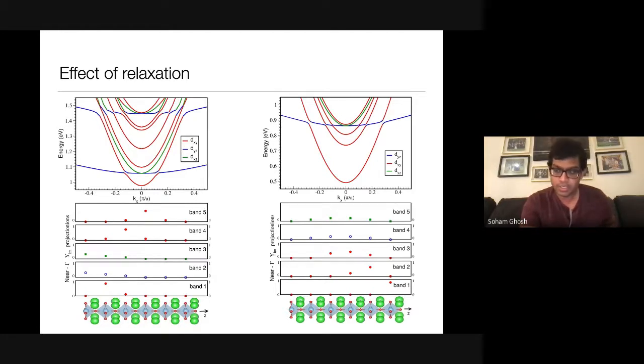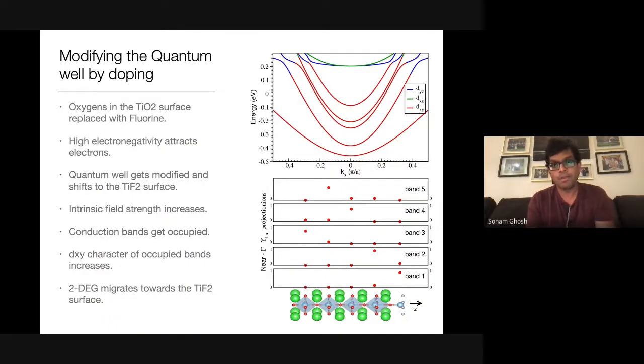And so what you see in these boxes, what I call band 1, band 2, band 3, band 4, and band 5, are corresponding to these points that go from these red ones. So you can see that the lowest band, the bands that you see experimentally, sit on the surface. And that's exactly what you see with experiments. If you're certain of this, what you can do to test this is to dope this, to modify the well. So for example, I doped the titanium oxide surface with fluorine.